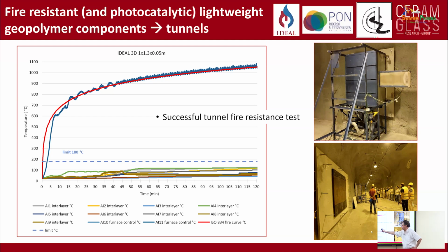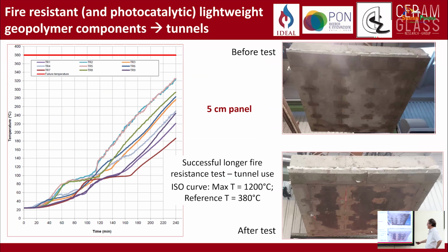So you have a crossover at around 90 minutes. So it depends on the application, but this was a successful test. You can see here the curves for the 5 centimeter panel. A maximum temperature in this case of 1200 degrees, and the temperature should not have become higher than 380 degrees. So this was again a successful test.